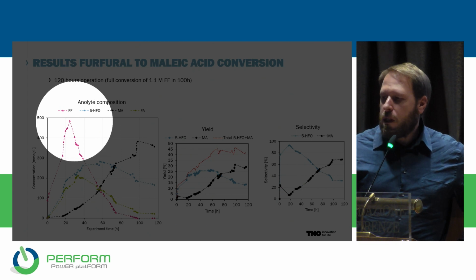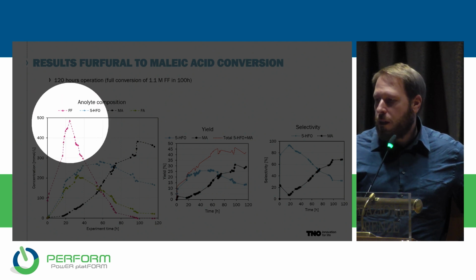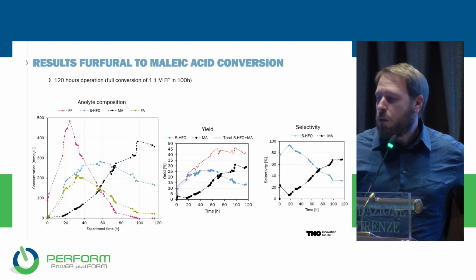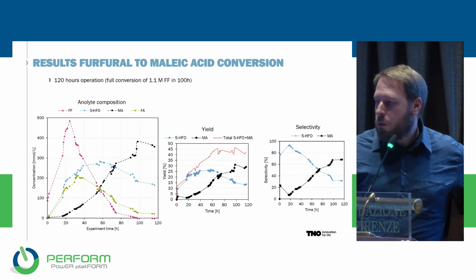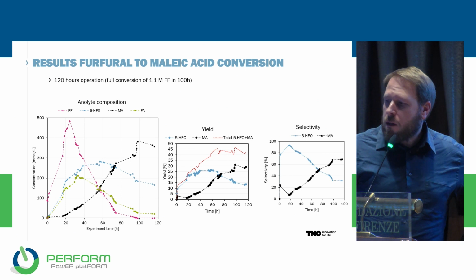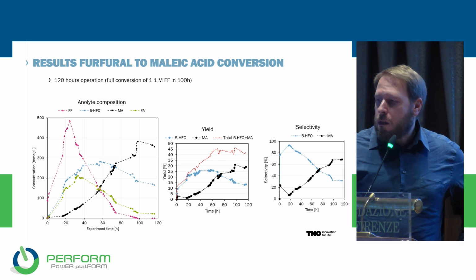However, after the first 20 hours, we have dosed in the needed furfural that we envision to use. And so afterwards, you see that the furfural goes down in concentration because we are consuming it. And eventually, after 100 hours of experiment, we consume all the furfural that we have in solution. Okay, so now if we look at the products,